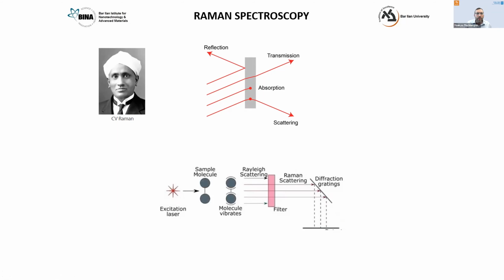However, what Raman realized is that a slight fraction of the scattered light is actually shifted to different wavelengths due to the fact that the materials itself have their own internal vibrational resonances. And so if you have a setup where you shine a laser on a material and you block carefully the laser light and also the Rayleigh scattering, which is coming at the same wavelength you put in, you can see these small changes in wavelength due to the Raman scattering.